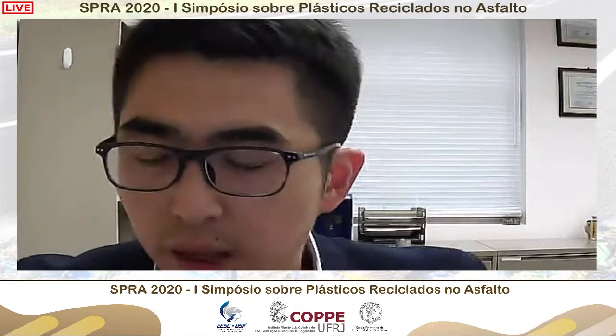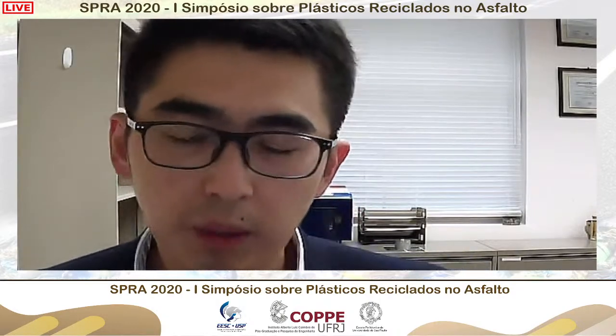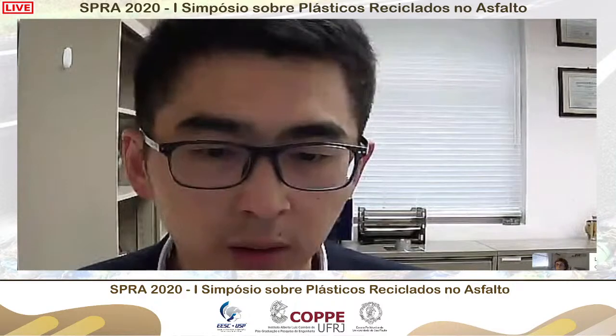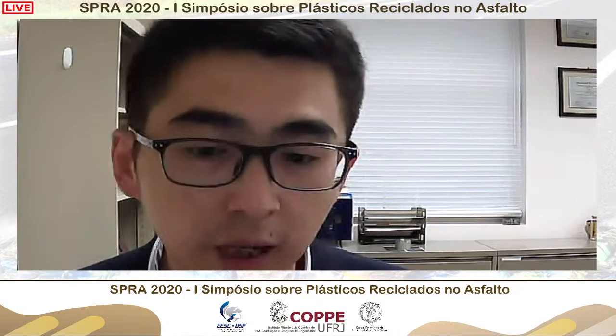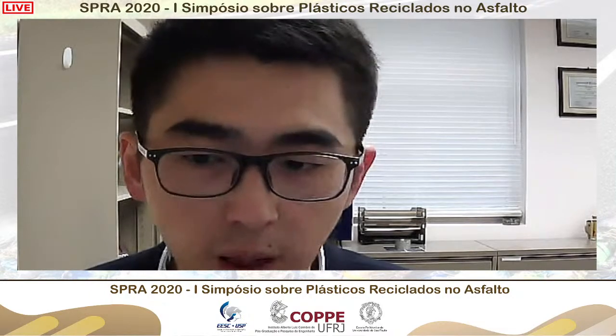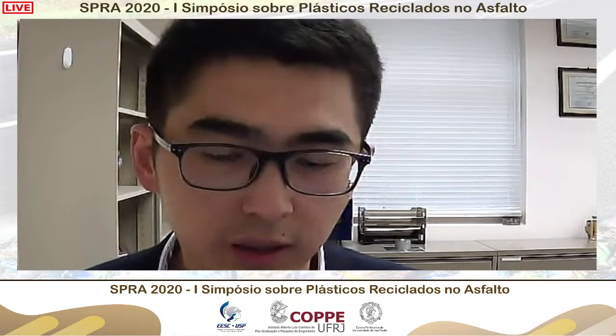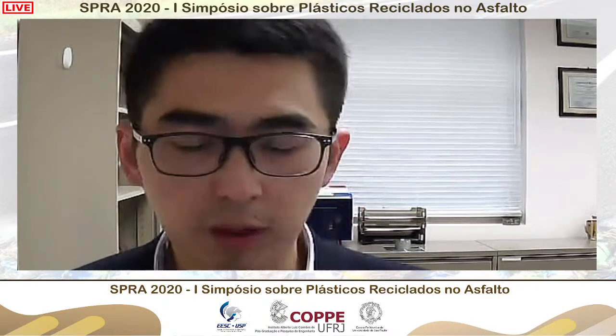Yeah, I think there are two parts that can play a role here when we talk about the reduced fatigue resistance. One is the overall stiffening impact. I think Raquel showed the result on the binder side that shows the plastic definitely makes the binder, the liquid, stiffer. At the same time, what we saw on the cyclic fatigue data is, before we run the damage mode, we look at the non-damage relaxation property. And we realize adding plastics has a detrimental impact on the relaxation property. So, the overall stiffening impact and the relaxation property, those are the two factors, I think, causing the reduction in the fatigue resistance. This is something we definitely need to be very careful about.